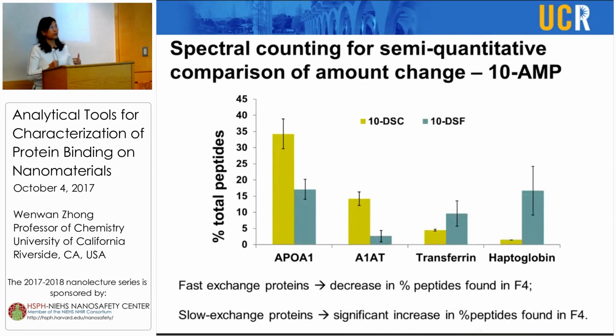We confirmed that by also doing spectral counting, a semi-quantitative mass spec technique, so we can compare the relative content of one particular protein in these two preparations. Indeed, for fast exchange proteins, we also confirmed this using capillary electrophoresis. Like I mentioned before, if you have very fast exchange, you will only observe a mobility shift, but if you have slow exchange, you see the bound peak very clearly in CE. So for those four proteins, we actually confirmed their binding kinetics in CE.